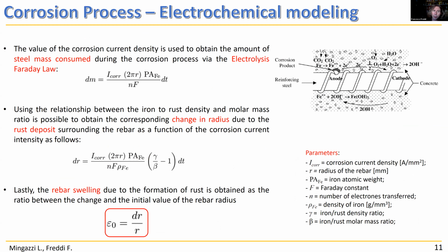The current density value permits to determine, via the Faraday law for electrolysis, the changing radius of the bar and the metal elements. So starting from the initial position and the initial radius of the bar, is it possible to determine the expansion in the bar? That is the crucial element for determining the initiation and the propagation of crack within the concrete element.